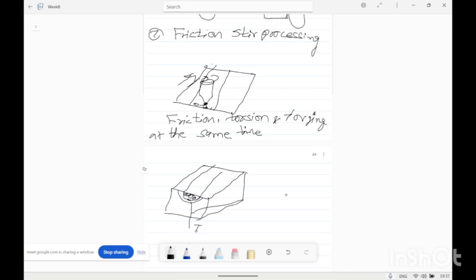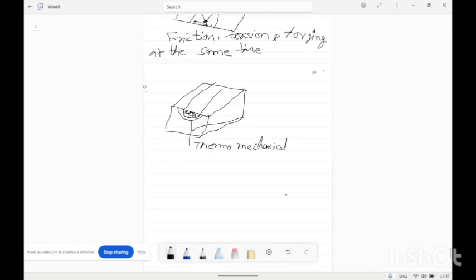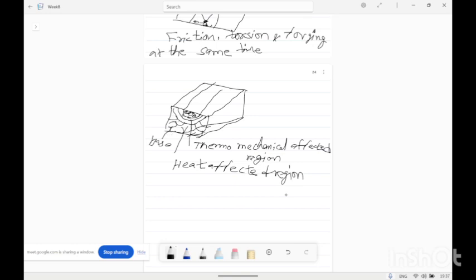Near this there will be the thermomechanically affected zone. Then far from that, there will be the heat affected region. And this will be the base material. So in the base material the grain size will be high, and as we move from the base to the heat affected zone, thermomechanically affected zone, and the friction stir process zone, the grain size will decrease significantly.